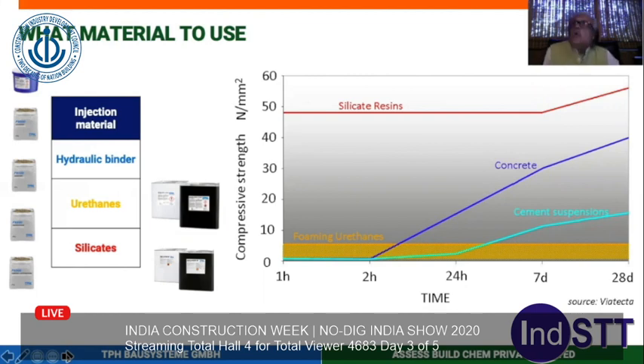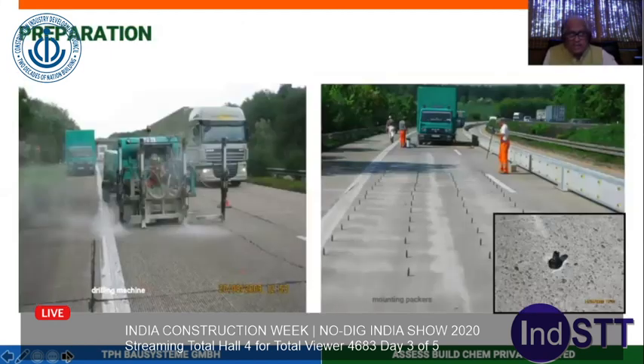If you use a good concrete, after 2 hours it starts setting. But before that 2 hours, if the water pressure is high, it can be thrown out. But if we use the silicate resins, you can see within 1 hour or within 2 hours, it can develop a strength of up to 50 newtons. It is very important to select the type of material. This is where it is settled.